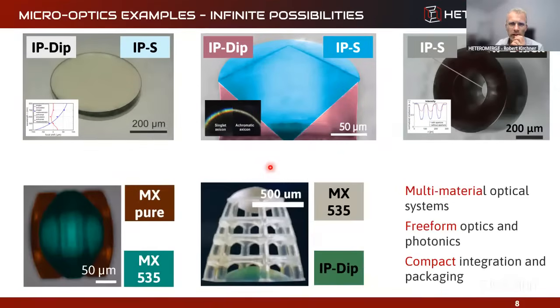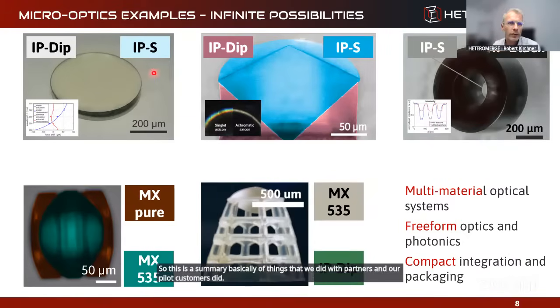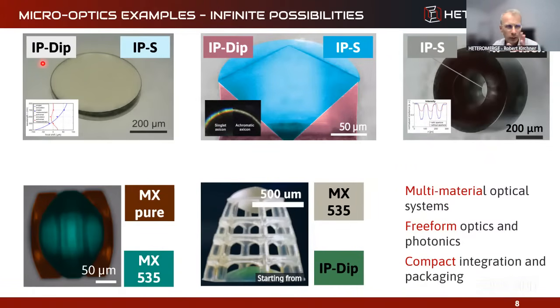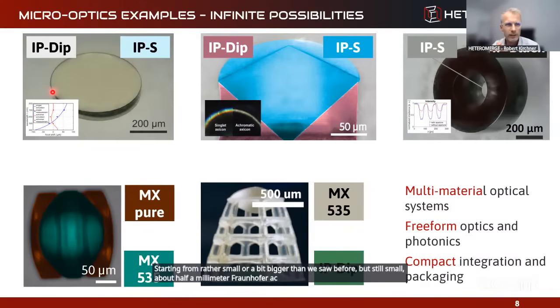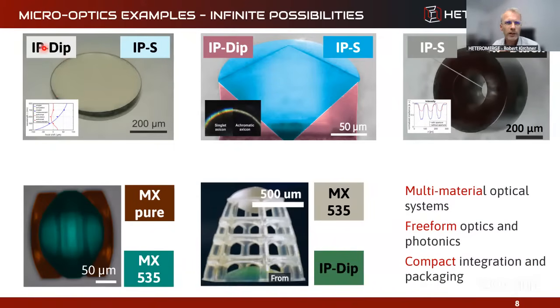So this is a summary basically of things that we did with partners and our pilot customers did. So if I go through step by step, starting from rather small, or a bit bigger than we saw before, but still small, about 0.5 millimeter Fraunhofer achromatic system. So we basically have two lenses, like a negative and a positive lens combined together, also spherical surfaces in this case, from two commercial materials with very interesting dispersion properties. So we can make an achromatic system.